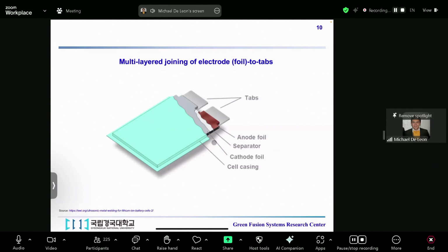To replicate actual battery conditions, we created 4 distinct configurations. The first two are layered copper to copper joints, known as similar welds, and the other two combine copper to aluminum stacks, or dissimilar welds. The differences vary depending on which material faced the ultrasonic horn during welding.